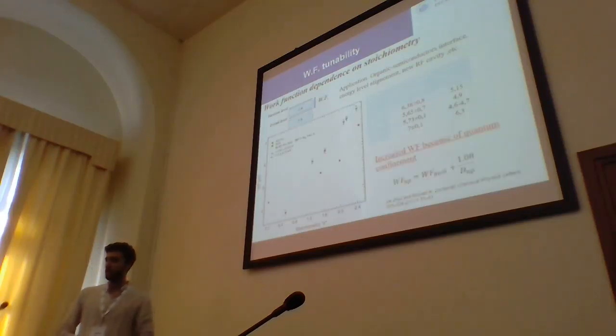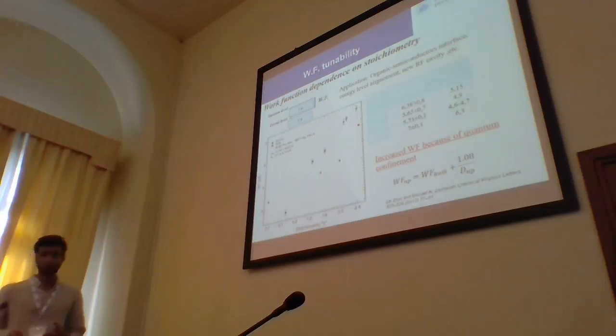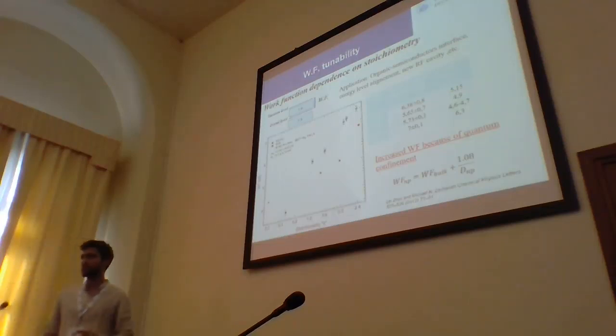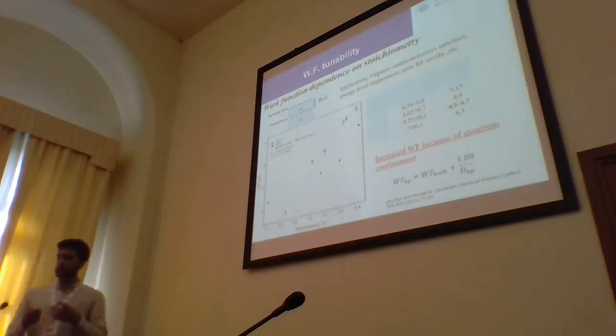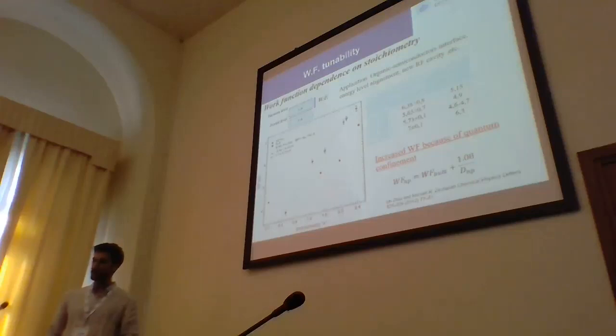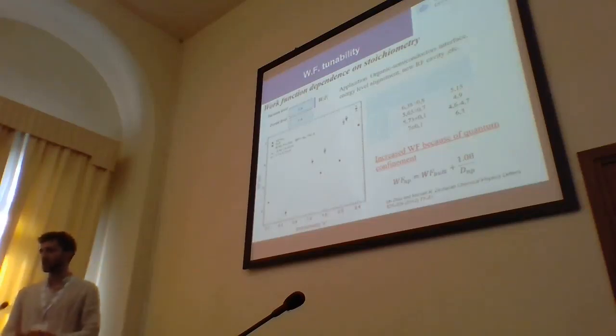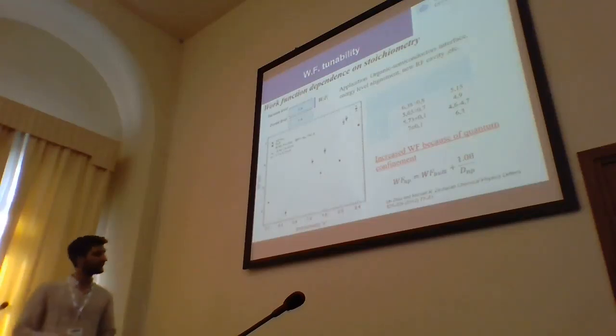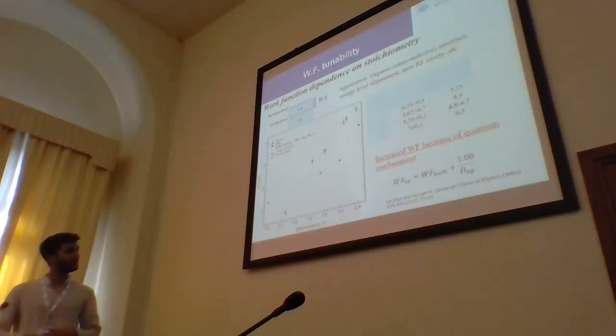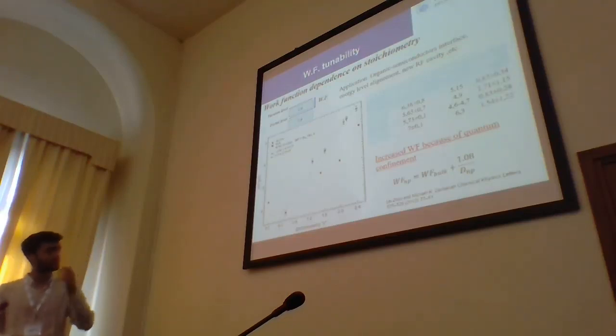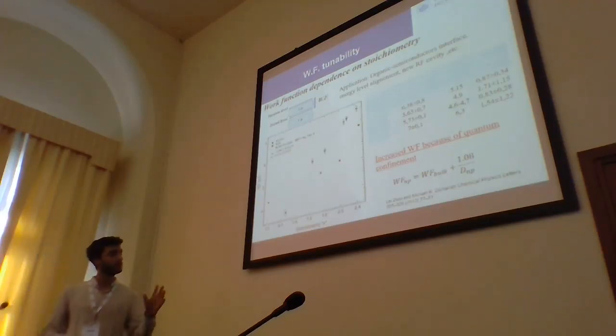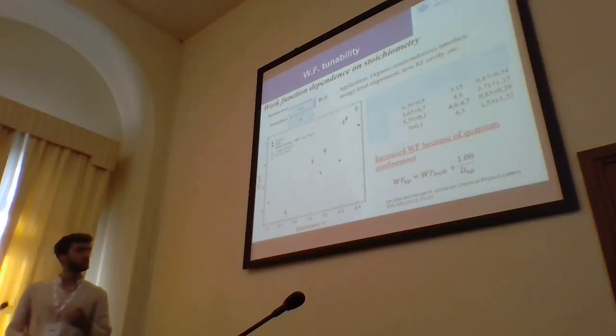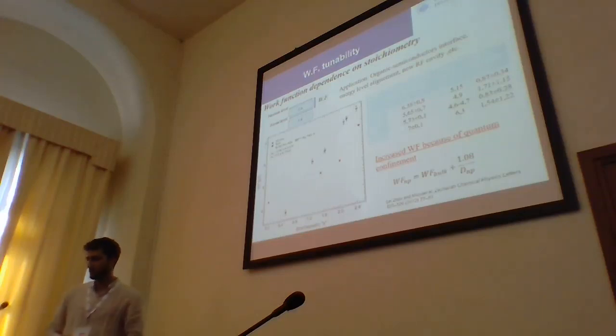This is because our samples are nanostructured, which means that they are formed by nanoparticles, and there is a strong quantum confinement effect which enhances the work function. And using this relation that Zhu and Zachary have found in literature, we can also extrapolate the diameter of these nanoparticles. So you can see that as a function of the oxidation state it is between 2 nanometers and 1, more or less.